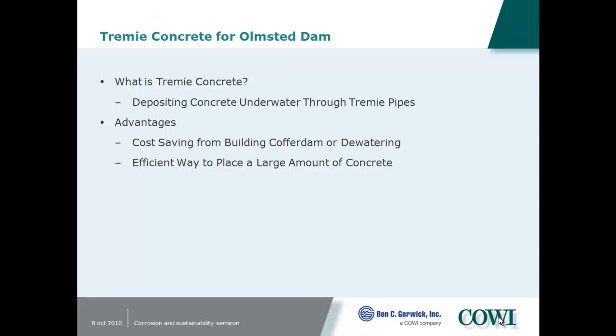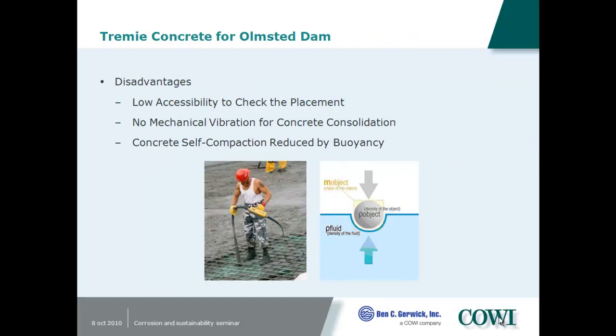For those who don't know, Tremie concrete is placed through Tremie pipes to separate the fresh concrete from the water, and then you form a seal, so you're always placing concrete into previously placed concrete, so it's not mixing with the water. Some advantages are you don't have to have a cofferdam, but you often use Tremie concrete to seal a cofferdam as well. But in this case for Olmsted, we don't even have a cofferdam. And it's an efficient way to place large volumes of concrete.